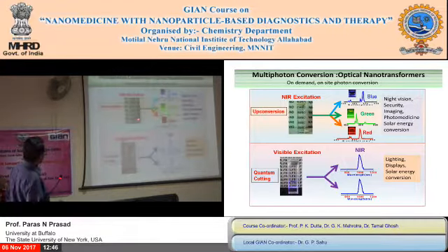Right? So we make them, and these nanoparticles generally are anywhere from 5 nanometers to less than 100 nanometers, depending on what we want to do with them. Okay, and these nanoparticles then have a coating on the surface. That's what's called surface chemistry, with ligands or surfactants, which make them dispersible in solvents so that they don't aggregate together. They're held separately. Okay, and for water, we want to have a surfactant whose outer part is hydrophilic, so that they can disperse in water, right?